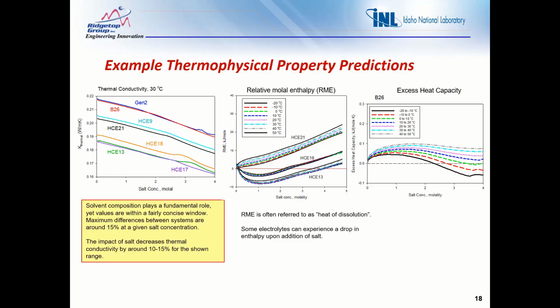In the middle, we have the mole enthalpy plotted up. We see in some cases it can go negative, which is perfectly viable in thermodynamics, and then it can increase and become more positive. And then lastly, we have excess heat capacity listed for one of our electrolytes called B26. It's a multi-solvent fast charge electrolyte. We show how that heat capacity changes over concentration and temperature. Next slide.